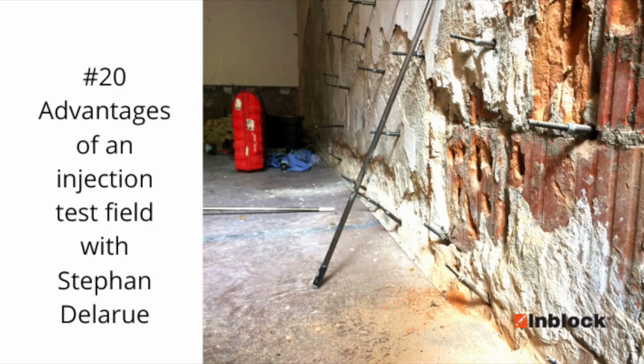That was also on an airport. The crack repair has to be done without any packer installation, so you only have to fill by gravity. Therefore, we did some tests there. We prepared some cracks, some meters of cracks, filled them with an epoxy resin, and did some core drillings to find out if we are reaching the depth which is necessary to strengthen the structure.